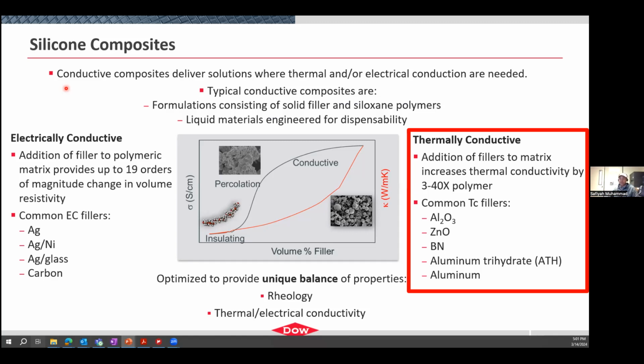And so these materials are a very interesting material. It's a liquid that we engineer very well so that it can be easily dispensed, but once it's in place, it almost sits as a solid, right? And so these are highly filled systems. And for thermally conductive materials, we will fill them with thermally conductive fillers inside of a matrix that is our silicone material. And so there's a lot of engineering to make sure that we balance out the property. So how well it conducts thermal energy versus the actual rheology or how the material moves when it's under pressure.